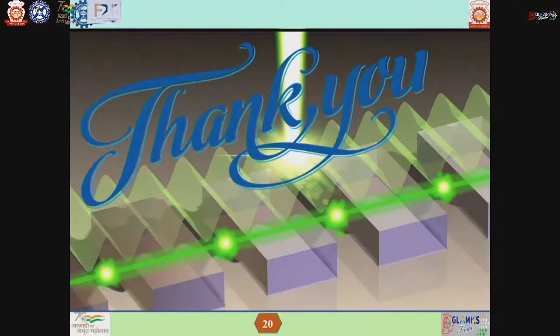Your main target is to produce an Er:Yb glass laser for high average power, right? So in that case, the facilities usually use Nd glass, right? So how much have you reduced the thermo-optic coefficient? In commercial laser glasses, it is normally around 11 to 12, times 10 to the power minus 6, but we have achieved 6.4. So almost half. Yeah, almost half. Nice.